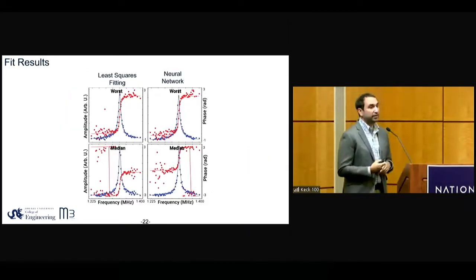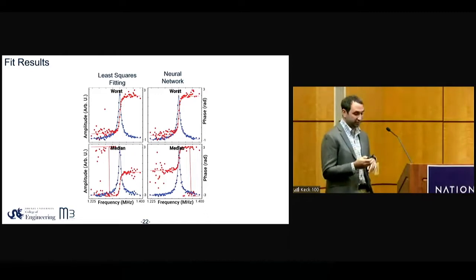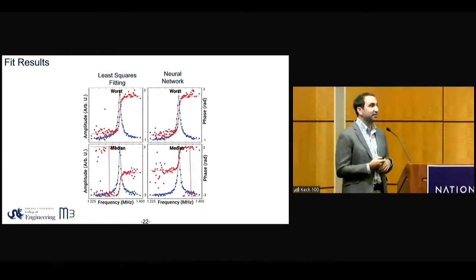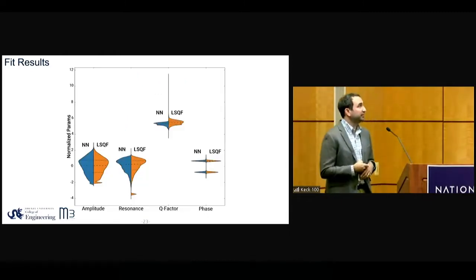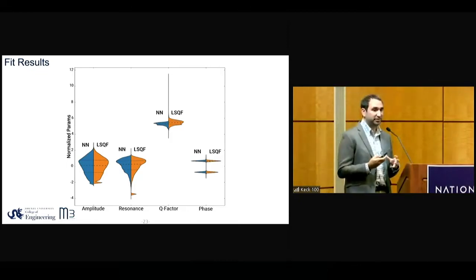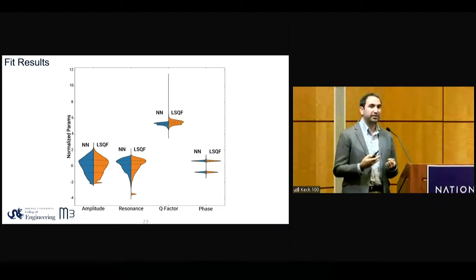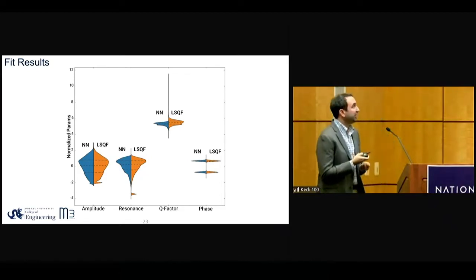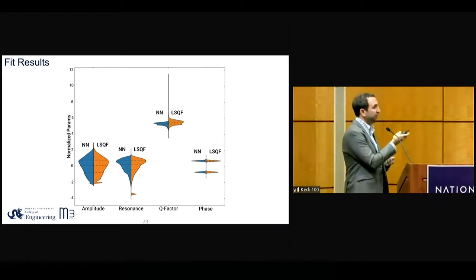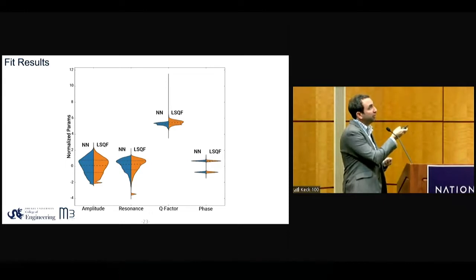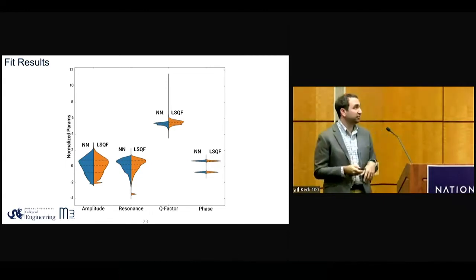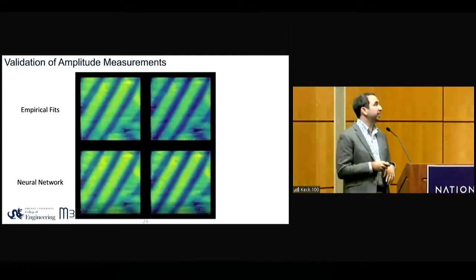So if we look at the results, they look essentially the same as the least squares fitting. That's what we would expect. But things get a little more interesting when you look at the distribution. With least squares fitting, you're really reliant on the initial guess. If your initial guess is wrong, you get trapped in a local minimum, and then you get responses that look like this that are not physical. So these tails of the distribution are actually bad fits. The neural network on real data always tends to be much more uniform in distribution. So that's a little hint that it's maybe doing a little better in some ways.